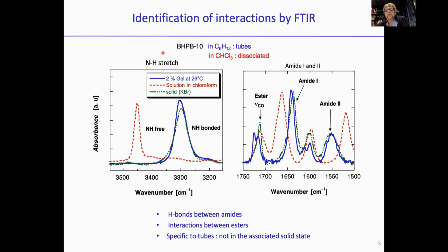Now, what we have done with these objects is to try to understand the interactions between the molecules. To probe the interactions, we performed some FTIR experiments. Here the blue spectrum corresponds to the tubes that you just saw, so it's gels at room temperature. You can see in this area the NH stretching band of the amide group, and these are the amide 1 and amide 2 bands. The shifts are coherent with the fact that all the amide groups are bound together by H bonds.